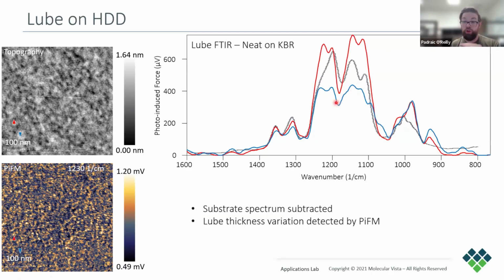Now the spectra taken on and off the bright regions on the PiFM lube sample, so these are the red and blue spectra respectively, they show a change in the lube peak intensities, and this is actually related to the thickness variation of the lube across the surface.